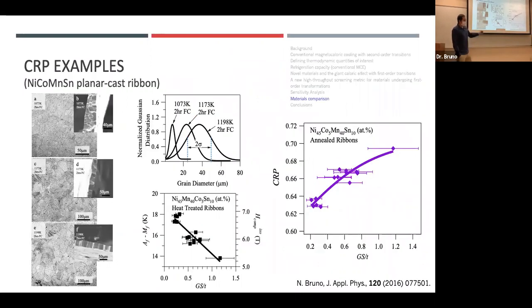So I've used this parameter for quite a few years to see how my secondary processing or my processing influences the refrigeration performance of some materials. I've used this on planar cast nickel, cobalt, manganese tin ribbons, where I grew grains with secondary heat treatments, and I found that I get a higher performance, better performance, with the larger grain size to thickness ratios of my material. So the microstructure in materials actually influences their magnetocaloric performance.